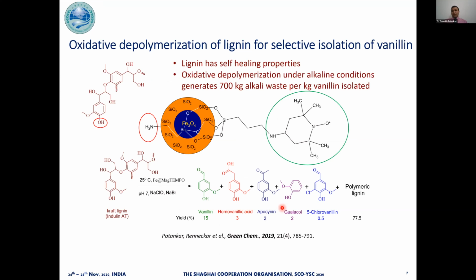Continuing this work on making high value chemicals from agricultural waste, I focused on this step of making vanillin from the lignin. So I tested the efficacy of the oxidative depolymerization of lignin using the same anchored TEMPO catalyst. Now this catalyst has free amine groups on it on which the TEMPO is anchored. And so I thought that these amine groups might be able to give the basic sites which are essential to abstract the protons from lignin and then start the oxidative depolymerization using the redox sites which are given by this TEMPO.